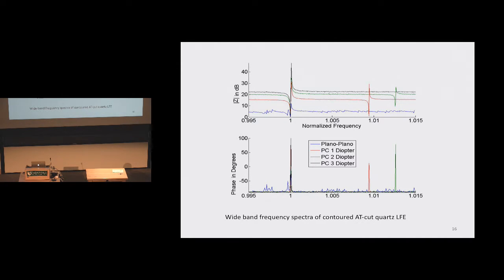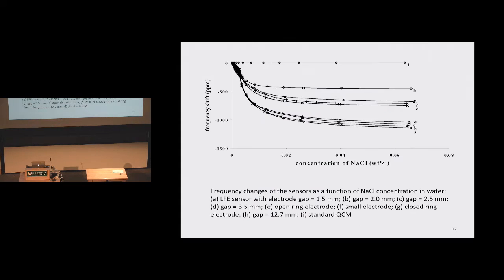You might say, well, why don't you go higher than 3 diopter? Why don't you go 4 and 5? Too much of a good thing. What happens is it focuses the energy almost to a point, and the actual active surface sensing area has decreased. So what we found was 3 diopter was the optimum curvature. Well, how does that work?